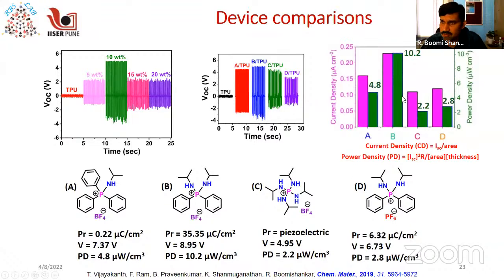Okay, so these are all plotted for comparison, and we see that the best performance was given by the material with the highest ferroelectric polarization, which is the diphenyl diisopropyl ammonium salt of the BF4 salt. So this tells you qualitatively that changing the ferroelectric remnant polarization changes the energy harvesting properties of the material. This is one observation that we have made in this particular contribution.